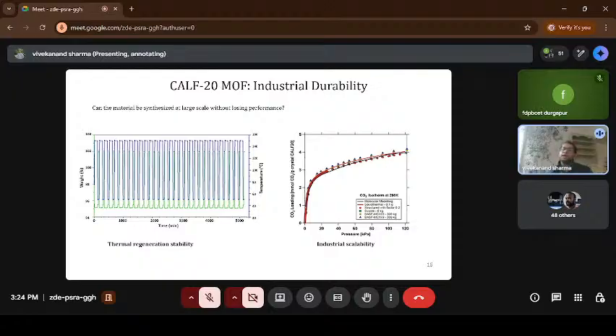Further, they scaled up, synthesizing this material on a very large scale using an industrial partner. From the lab-scale material or the company-built material up to 300 kg, all the materials give almost identical values of carbon dioxide gas uptake, whether coming from different batches from the company, from different government organizations, or from the lab. So all have performed at a similar level of carbon dioxide uptake. This tells the industrial scalability: this material is very possible to develop on a large industrial scale.